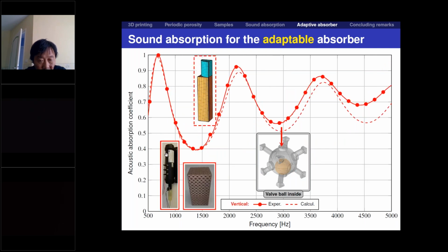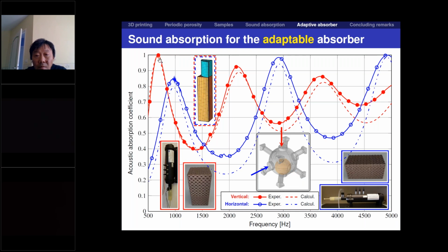And now if we hang the sample on the wall, this valve ball blocks the main path, and the airflow is directed into the skew channels, which have smaller diameter than the large vertical channels, and obviously the tortuosity is also increased. So we move these absorption peaks to other frequencies, which were, for example, the frequencies for some kind of noise conditions that we want to adapt to.